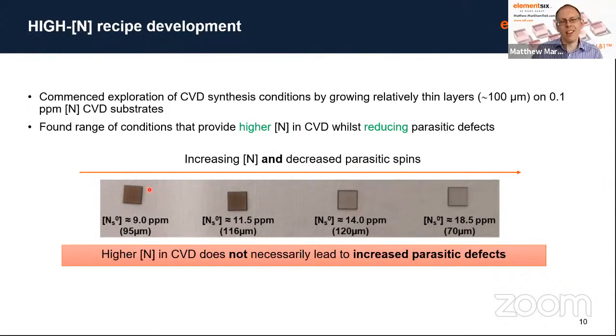The parasitic defects, things like vacancy clusters or NVH, typically produce a brown coloration, basically brown color centers, which cause a darkening of the material. What we can see in this plot is that as we change our conditions, we're able to reduce the amount of these brown defects while increasing the nitrogen content in the material, which is exactly what we want to do. We want a high nitrogen material with a low concentration of parasitic defects. So we were targeting something around 16 ppm.